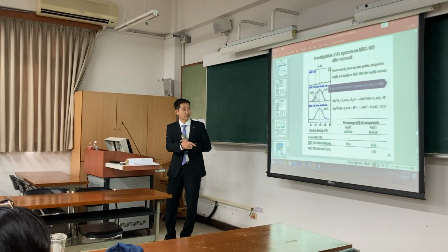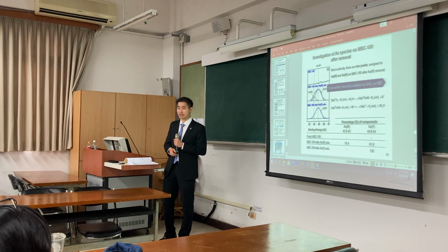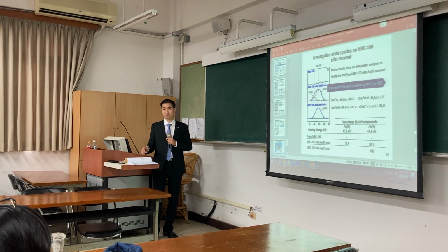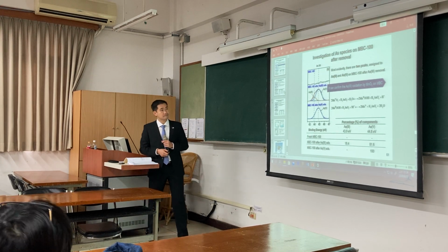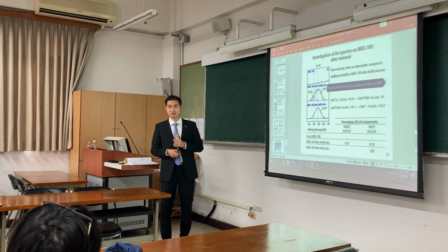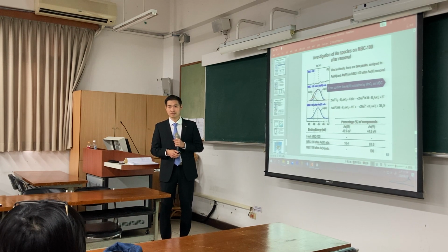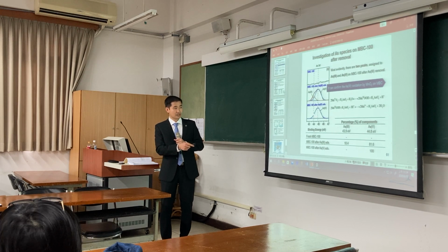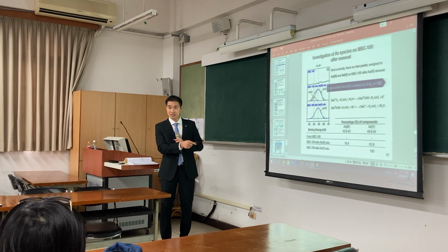So I observed two peaks. First is arsenic 3 and the second is arsenic 5 on the system of MnOx and arsenic 3. In the arsenic 5 solution, only one peak can be observed. Only arsenic 5. We cannot see arsenic 3 here. This is evidence. This one starts from arsenic 3, and this one starts from arsenic 5.